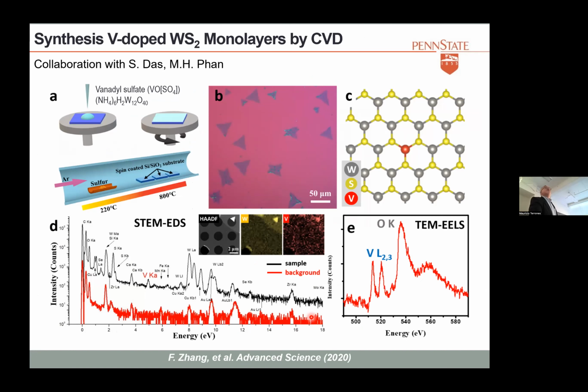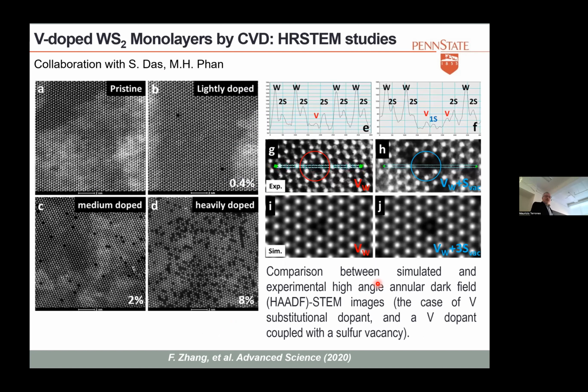So in this case, we use ammonium metatungstate, which is the tungsten precursor, and then vanadyl sulfate, which is the vanadium precursor. We use the system that I showed you. We vaporize, and then we can see the signal of vanadium here by EDX. But what is more interesting is that we have here some examples with 0.4 atomic percent of vanadium. We can have 2% of vanadium and 8% of vanadium.